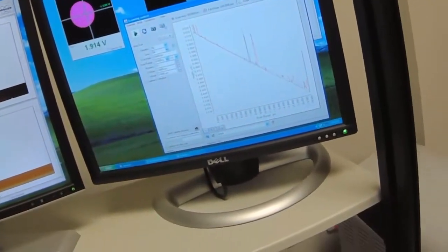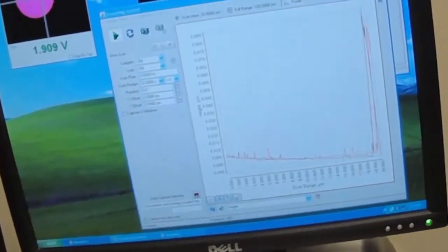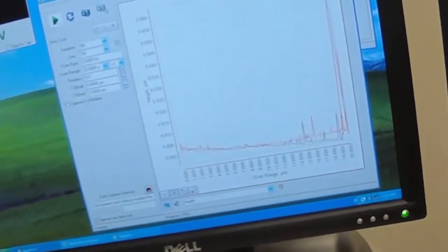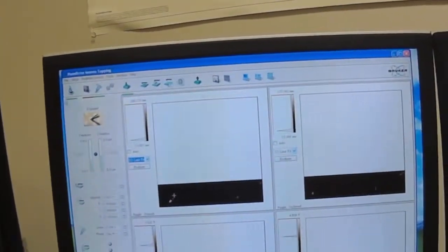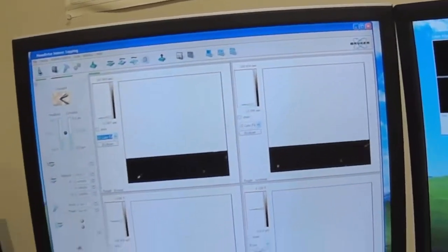Also notice that our flat surface is not level, but we can fix that with the software. So over here we can do a line fit, and let's do that here as well. Now that flattened it out pretty well, and now we can see these spikes a little clearer, how they're sort of lining up, they're just shifted a little bit. And up over here we see the spikes look like dots. So what we want to do is measure the size of these bright spots, because those are objects, spherical objects. If they're circular spots, then that means it's a sphere, and that's probably our nanoparticle.